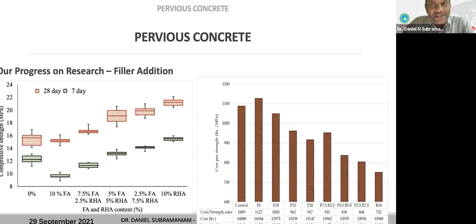But in the other studies that we showed before, we used aggregate sizes from 12 to 25 millimeters. So those are very huge aggregates. And on the right, we have the cost of using them. So we can see that using 10% of rice husk ash is going to give us the lowest cost. So we can actually find out the economy that we're looking for.